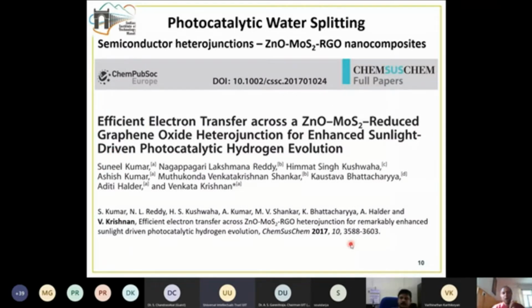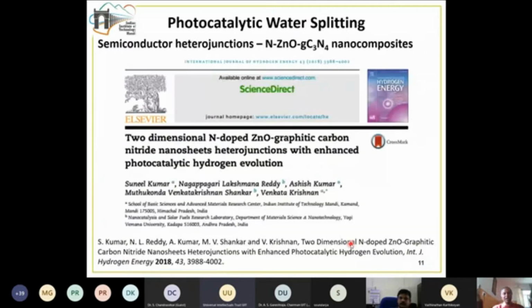Now we thought, okay, we have this ternary nanocomposite, or in fact a quaternary nanocomposite. Can we do the same thing with just a simple 2-component system, a binary nanocomposite? So in order to do that, again we took this zinc oxide, and this time we doped this zinc oxide with nitrogen, so that the valence band position is slightly modified and the band gap gets reduced. Then we coupled it with another visible light active semiconductor, graphitic carbon nitride, and prepared a nanocomposite using these two materials, N-doped ZnO and graphitic carbon nitride.